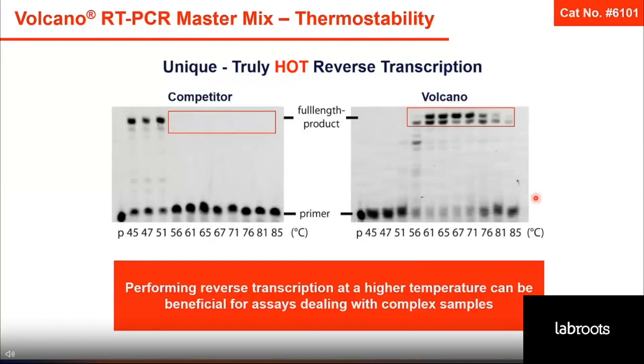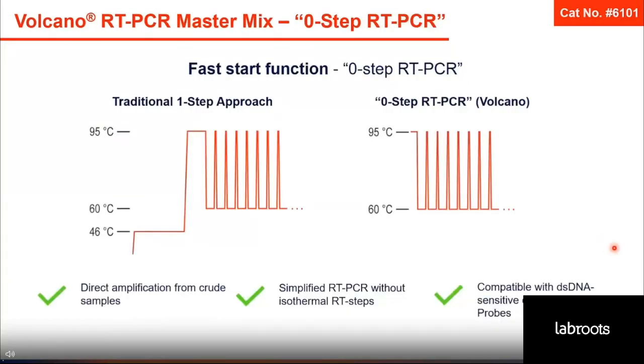So again, performing reverse transcription at this higher temperature can be beneficial for assays dealing with complex RNA samples, but also you have to keep in mind that at these higher temperatures, no RNase activity is observed. So it gives you also higher specificity of the assay. Another benefit of reverse transcription at higher temperature is that you don't have to perform an initial isothermal reverse transcription step and then follow with cycling for DNA amplification. You can combine all of this within one step. So you can use the so-called zero-step RT-PCR protocol, where reverse transcription and annealing extension take place at the same temperature simultaneously. So this gives you also shorter protocols and saves time to results.